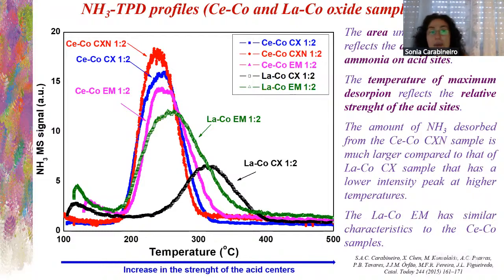We also did ammonia TPD profiles. So ammonia is adsorbed, and then we make a desorption. The area under the TPD curve reflects the amount of adsorbed ammonia on acid sites. The temperature of the maximum desorption reflects the relative strength of the acid sites. That means that there is an increase in the strength of acid sites with the desorption temperature. So we see that the amount of ammonia desorbed from the CeCo sample is much larger compared to the others. The LaCo sample is different. So these ones have less strength, the acid sites are weaker, shall we say.